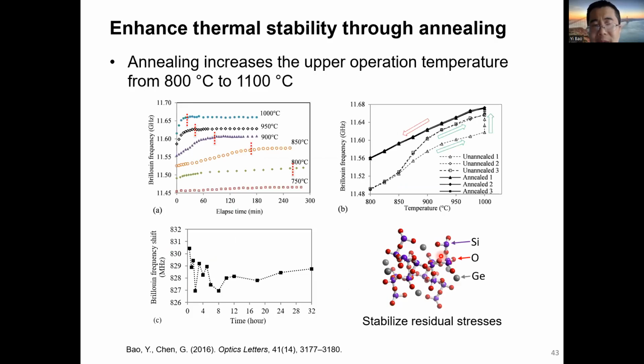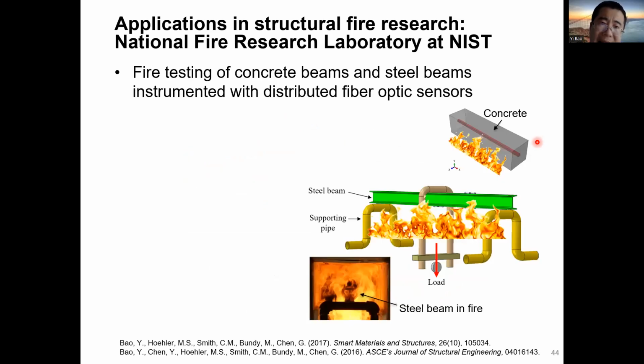So we proposed a method based on thermal annealing technique to stabilize the residual stresses. And therefore, we increased the thermal stability of the fiber optic sensor. So after that, we were able to use the sensor to measure temperature higher than 1,000 Celsius degree. Therefore, the sensor was able to do the measurements in fire hazards.